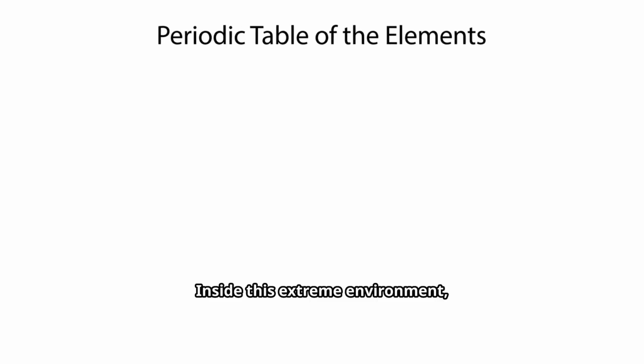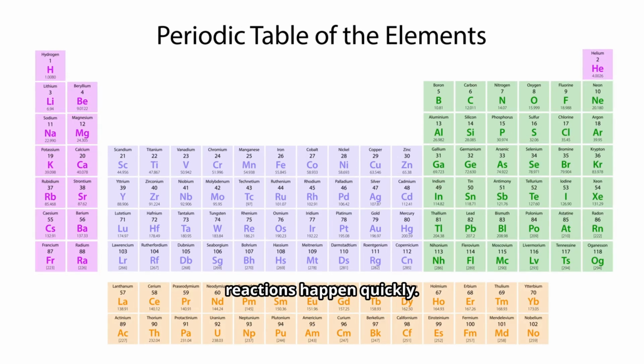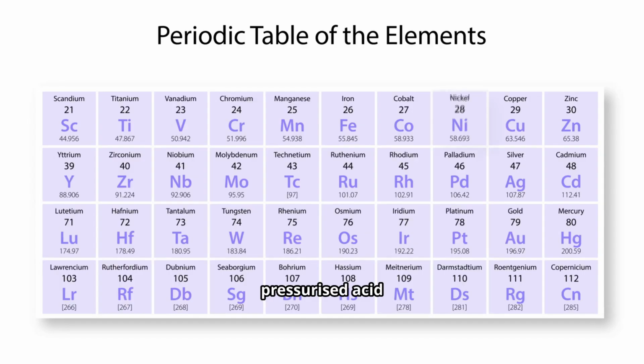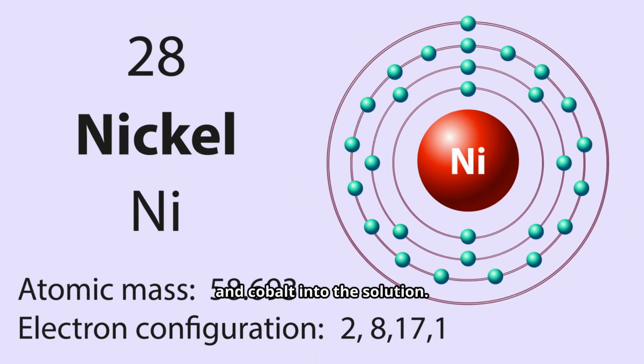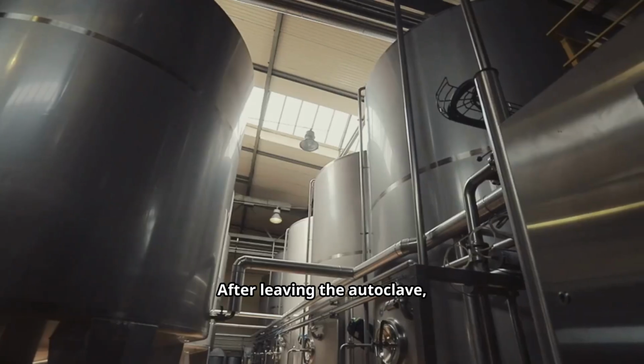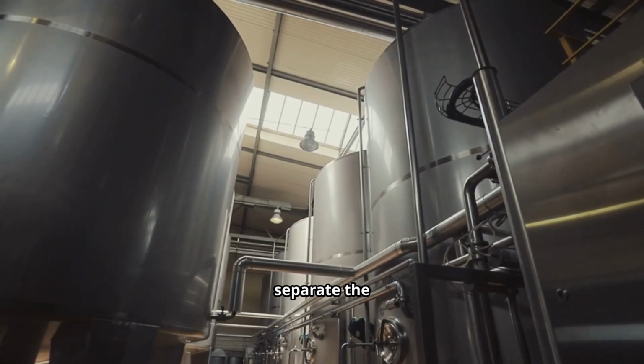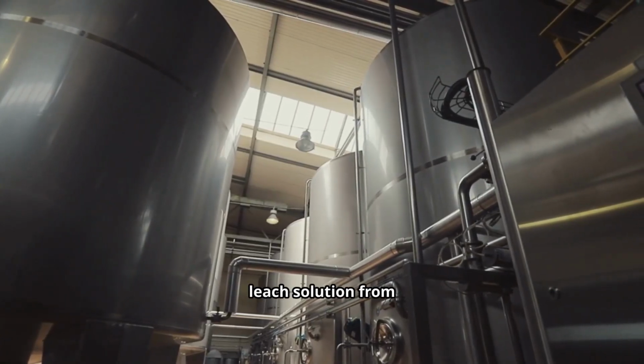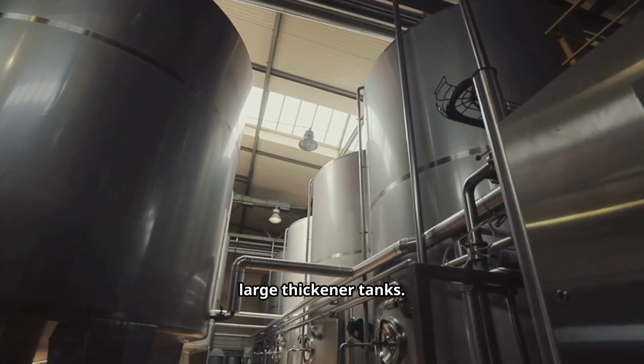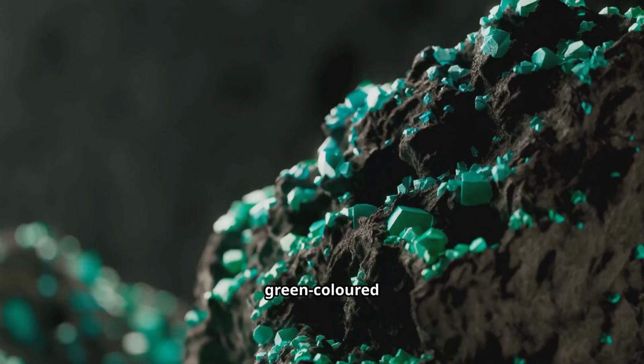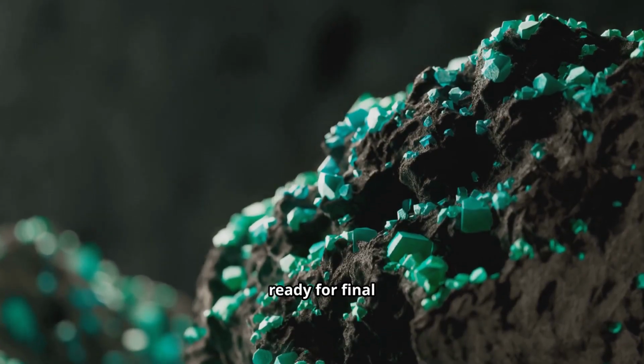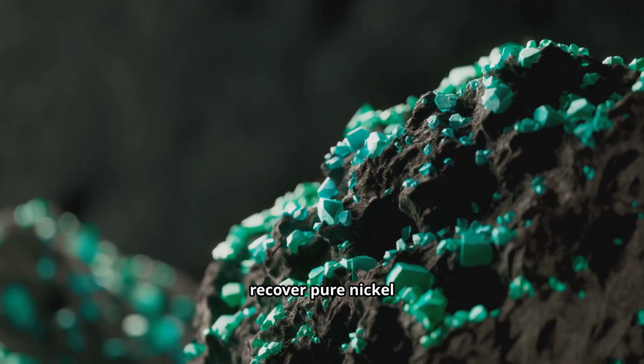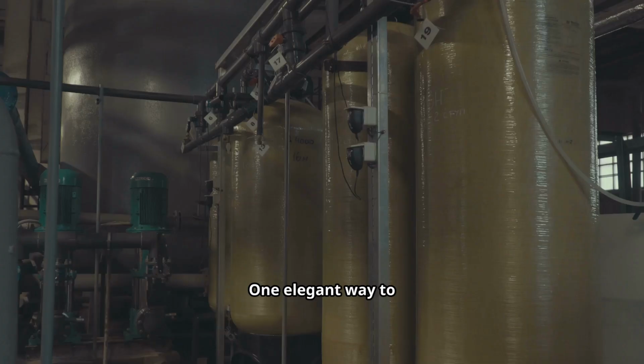Inside this extreme environment, the chemical reactions happen quickly. The hot, pressurized acid attacks the ore minerals, breaking them down and releasing nickel and cobalt into the solution. After leaving the autoclave, the next step is to separate the nickel-rich pregnant leach solution from the solid residue in large thickener tanks. The clear, green-colored pregnant leach solution is now ready for final purification to recover pure nickel and cobalt. One elegant way to recover the metal is electrowinning.